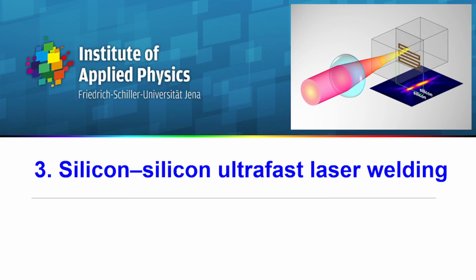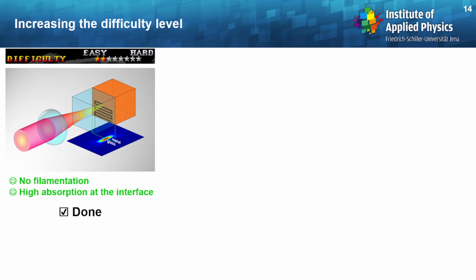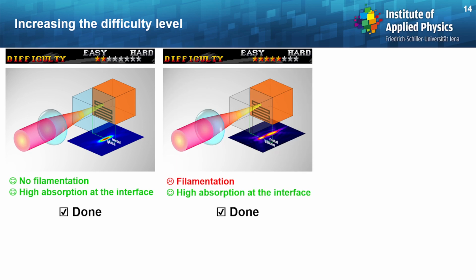Okay, with this, I will move to the last part of my talk, which is silicon to silicon ultrafast laser welding. To make a short recap, from the state of the art, we have seen that it is quite easy to join glass to metal because there are not many filamentation effects, and at the same time, you get some high absorption at the interface due to the free electrons of the metal. As we have just seen, in the silicon to metal configuration, we still have some high absorption at the interface because of the metal, but filamentation has to be accounted for when processing the stack of samples.